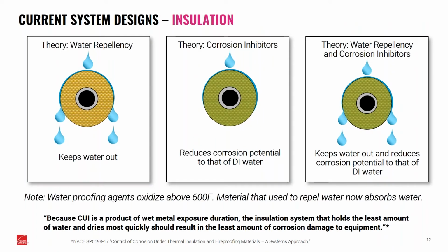Now, when we talk about insulation and water repellency, or how you design for moisture intrusion, there's usually three different ways that this is done, and these usually are driven by insulation types. One theory is that you use water repellency, and water repellency just keeps the water out. It just sheds the water away. That one seems to make the most sense. If it never gets towards the middle of the pipe, then you've done your job. The other theory is to use corrosion inhibitors. So if you have an insulation that might absorb more water, maybe you want to have something that has a corrosion inhibitor in it. So at least if any moisture does get into that system, at least it reduces the corrosion potential down to something like deionized water. So it's going to reduce that rate dramatically.